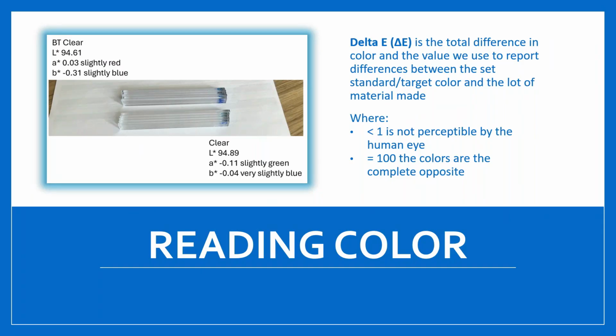And so depending on requirements that you may have, delta E values go from 0 to 100. Within certain markets where it's really important that the color stays very consistent, you'll see that typically a less than 1 delta E value is specified. And the reason for that is that you can't detect it. If you put your sample chip and the chip that they make of the new lot of material together to compare, and it has a delta E of 0.9, 0.8, whatever it is, as long as it's under 1, your human eye cannot look at the two chips and distinguish a difference between them. And so you have to map it on coordinates, LAB values, and compare that way because you can't see the difference. And then delta E goes all the way to 100, where you have a completely opposite color. And so depending on the end user specification or your specification, you might lock down a max delta E value for your color differences.